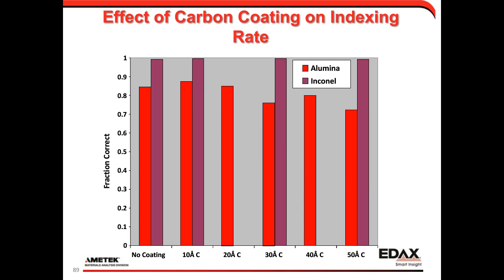And this looks at the effect of coating thickness on the indexing rates. And again, at that 20 angstrom level, we still get pretty reasonable performance compared to the baseline of no coating.